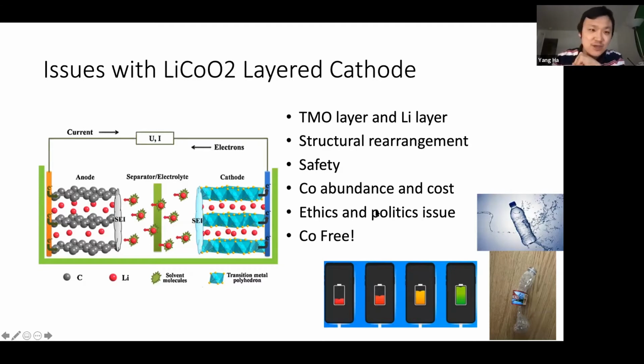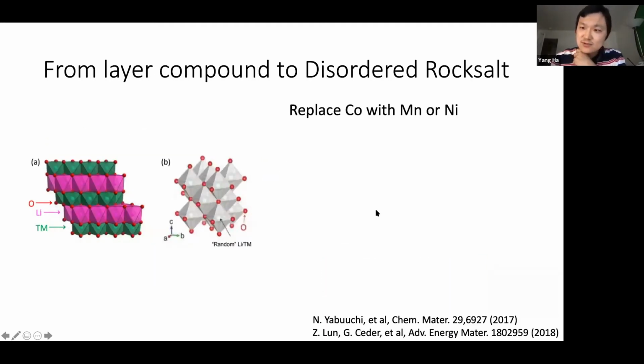So this is where we are. The first thing people would think is to replace cobalt with something in the same family, a 3D transition metal, with either manganese or nickel. So lithium manganese oxide is a good option. Plus, cobalt prefers the layered structure, while the lithium manganese oxide can have a disordered rocksalt structure, which is believed to be more rigid or more stable than the layered structure.